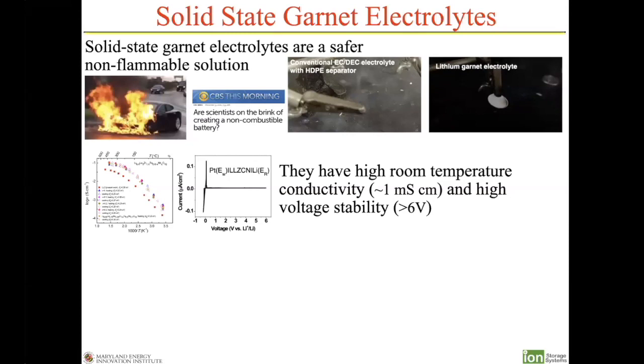It has quite a reasonable conductivity. And also has a voltage stability all the way from lithium metal all the way to over 6 volts. It's made from inexpensive elements. Lanthanum and zirconium are pretty cheap. The most expensive material in the garnet is the lithium itself, which of course you're going to have in any lithium battery. Plus, of course, you can have some dopants in there, but they're there in a smaller concentration.